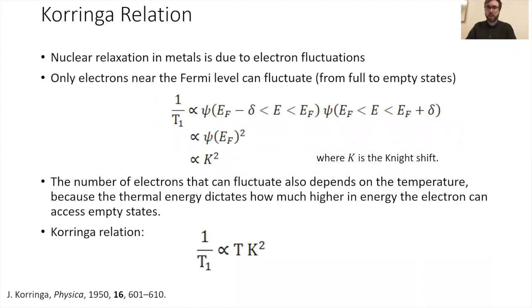And then also back in this first half, what determines the extent of direct and indirect Knight shifts? So that's really dictated by whether you have s orbitals. The first question is whether you have direct or indirect. To have direct, you need s orbitals at the Fermi level that are partially filled, and if you have that, the direct will almost always dominate. It's just a larger effect. The actual magnitude of a direct Knight shift is simply proportional to the s density of states at the Fermi level. And that's dictated by the dispersion in your band structure, but this is something you can measure or predict with calculations.